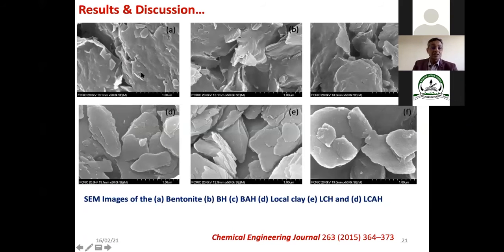So these are some of the results that we will be getting, the SEM images of the materials. This is the pristine clay, and these are the modified clay. You can see that it is getting more porous. Sometimes you can see very fine particles on the surface. That will be the organic molecule that has been introduced.